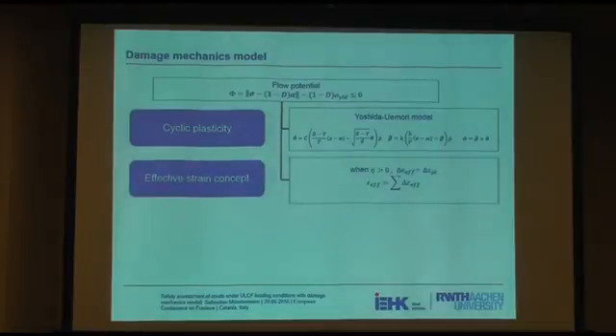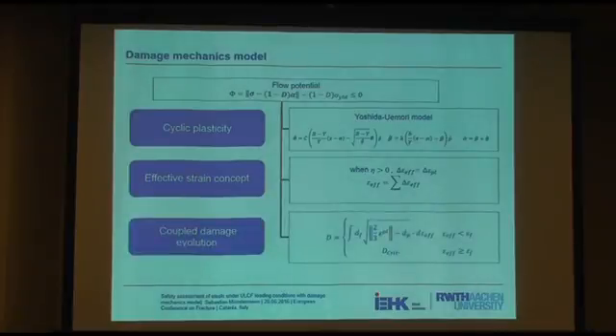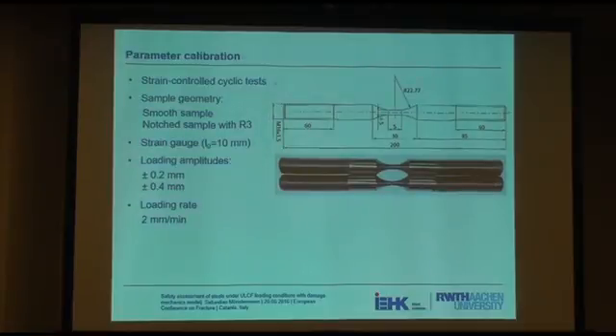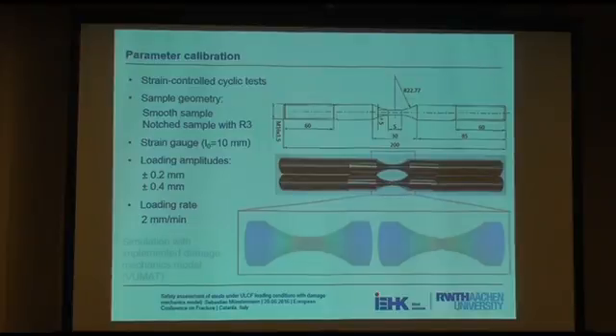There's the effective strain concept that I presented, and the ductile damage evolution law, and all this contains some parameters that need to be calibrated. All this has been done with the help of cyclic experiments with unnotched and notched specimens. We applied two loading amplitudes, plus minus 0.2 and plus minus 0.4 millimeters, at a rather slow loading rate.